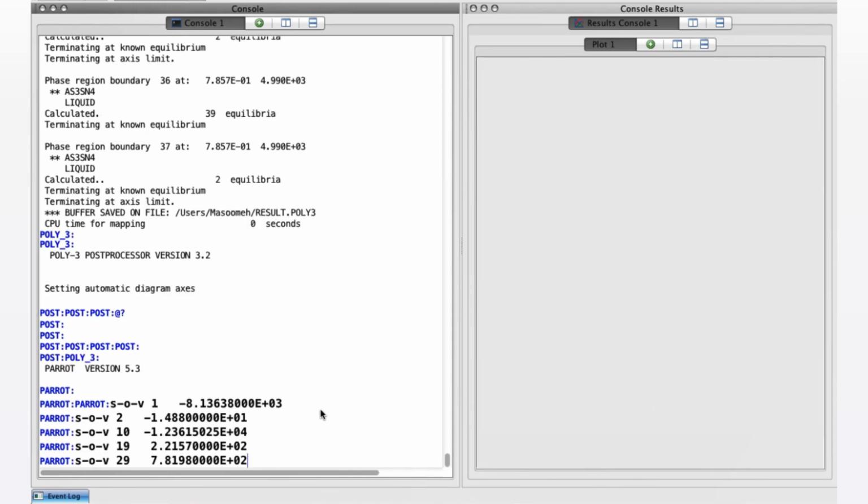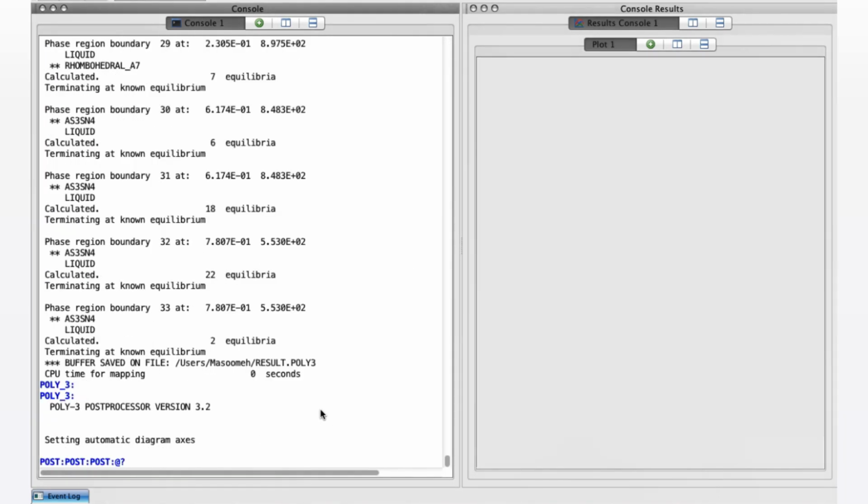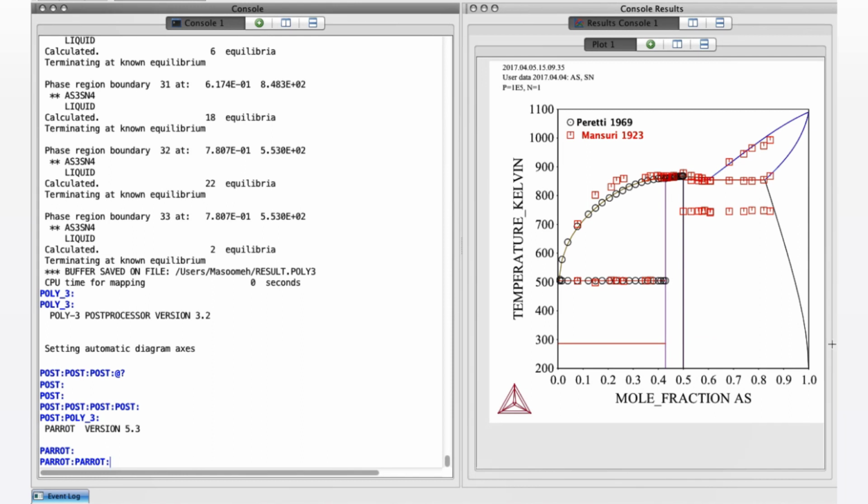Afterwards, the melting points and liquidus parameters are adjusted, and after this step, the phase diagram looks very close to the experimental data, and only fine-tuning of the variables is required. By the end of the assessment, usually all the variables are optimized together once or several times by using various weights on different datasets. A good practice for the final step of the optimization is to have all parameters rounded and only significant digits are kept.